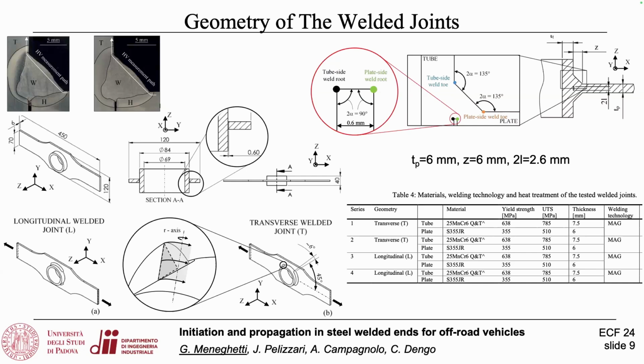But the root, due to the backlash, is not a pre-crack, it is indeed a slot. So the root has two critical points, at the plate side and at the tube side. So in the end, we have potentially 4 points in competition. And this is a very difficult problem to face using the design recommendations, which cannot solve the problem of finding the most critical point among these 4 ones.